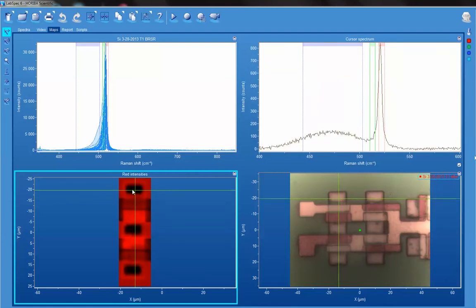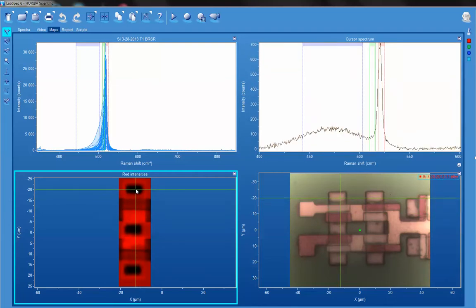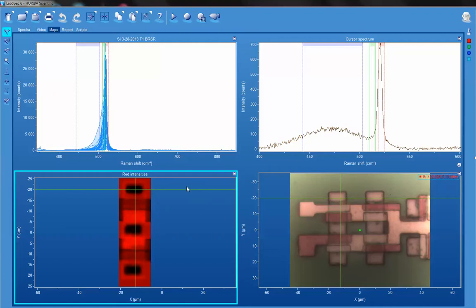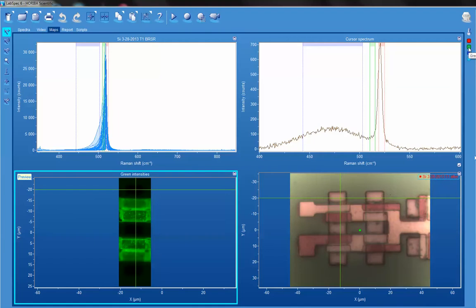Now, you notice I have a green bracket here. This green bracket will allow us to emphasize the polysilicon and its Raman shifts that are to lower energy, principally due to strain and small grain or domain size. If we click on the green bracket for our image...